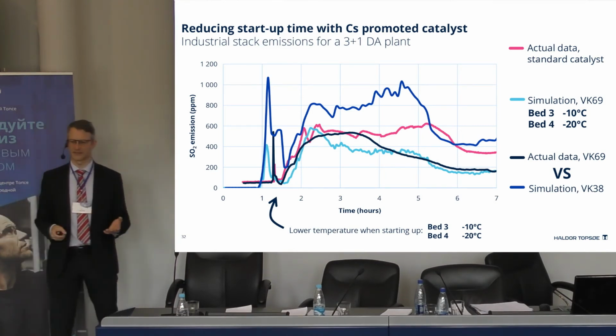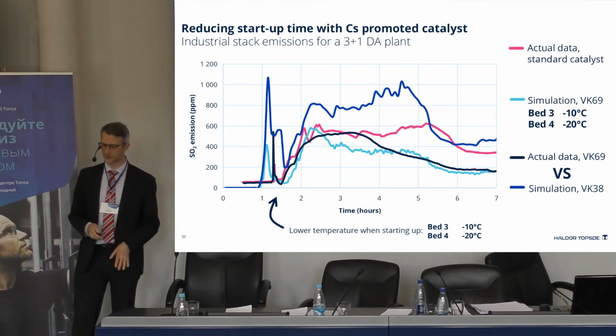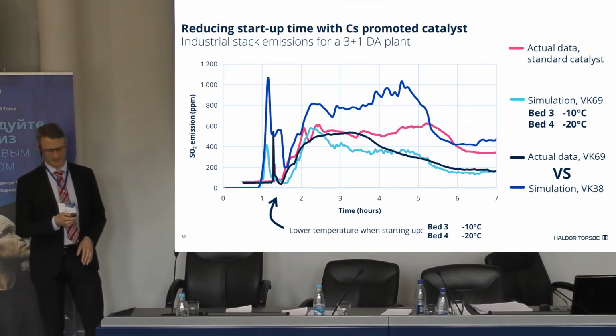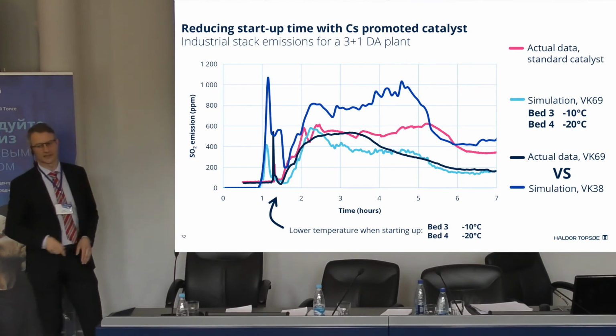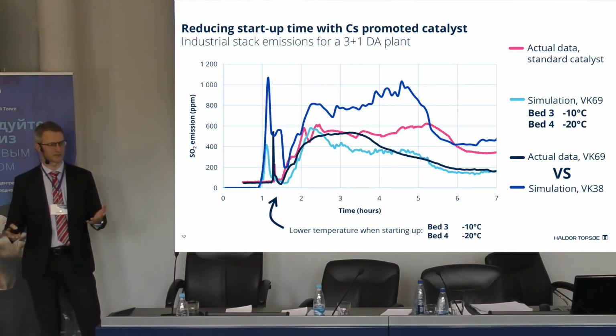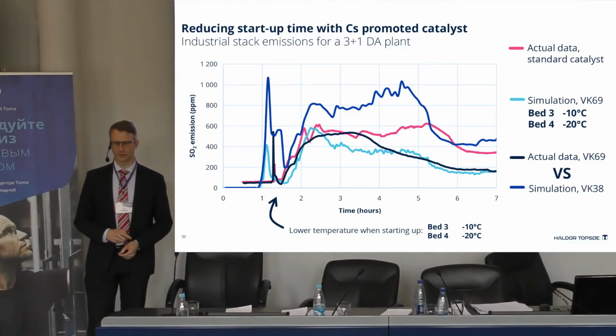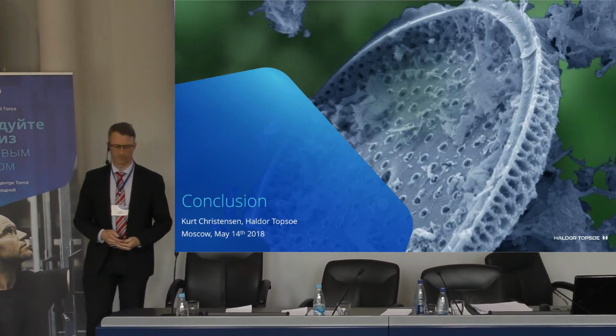Of course, they could have kept the potassium-promoted catalyst and just lowered temperatures, but the prediction says that this is what they'll get. So they will get very high emissions if they just lower temperature because the catalyst is not active enough. So this is another way where we can say what is the best choice of catalyst in a given situation for a given startup of a plant. Okay, that was another example of the dynamics of the sulfuric acid catalyst, but here more on the industrial scale, but still using the fundamental principles of the catalyst.